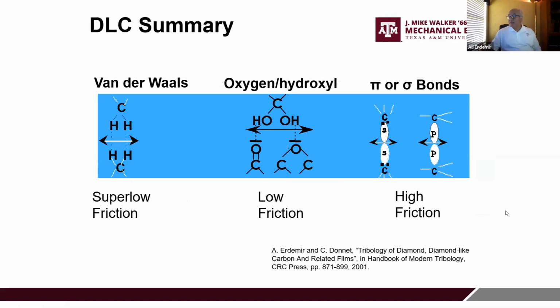So in the case of DLC, it looked as if superlubricity has a lot to do with hydrogen termination of the top sliding surfaces. You can also terminate these surfaces with OH or oxygen, which are not shown here, but we also did tests run in pure hydroxyl ion or pure oxygen. The friction coefficient would be low, but not as low as with hydrogen, mainly because even these oxygen or hydroxyl terminated surfaces would have some polar activity and attraction, and thereby their